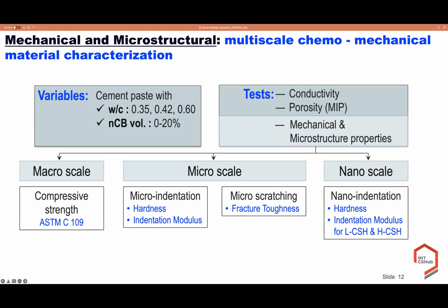By linking the macroscale to the microscale to the nanoscale, we get a full comprehension of the effect of nanocarbon black in the cement matrix. At the macroscale we measure the compressive strength, while at the microscale we measure the hardness and indentation modulus using a micro-indentation test, and fracture toughness using a micro-scratching test.